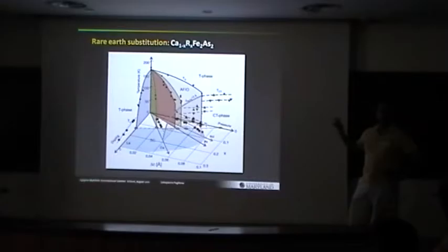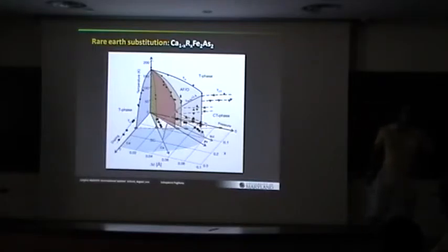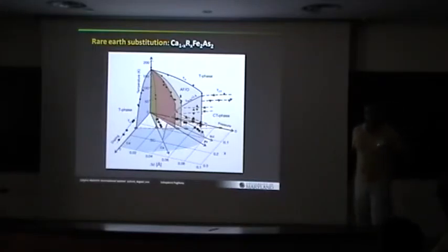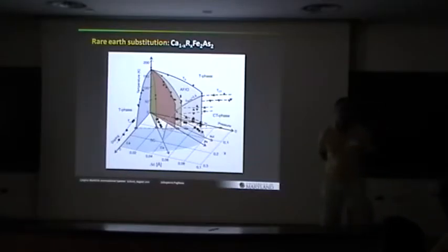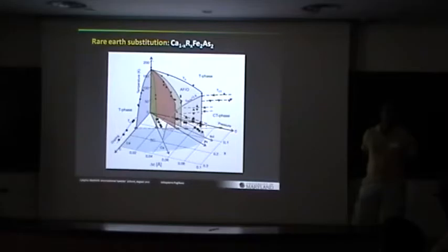But actually, our real motivation was to electron dope outside of the iron site. That's really why we tried to do it. Do you have any idea why that would give you what amounts to an extraordinarily high TC for the 122 family, modulo your caveats? Well, I think it's the same reason that the alkali metal substitution gives you up to 40K. So it's just less disorder. Okay, so you buy that kind of picture.